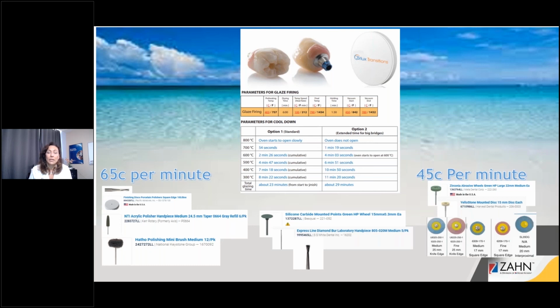And another thing we want to touch upon when glazing is if you have a bunch of single units, just like with the sintering, you can go a little bit faster when you have thin single units. On the chart, you can see that they're giving you the parameters for cool down. I just want to make it nice and easy for you, since everybody has different ovens and they all open differently, cool down differently. Just the basic rule of thumb is if you have singles and small units, 65 Celsius per minute cool down is acceptable.